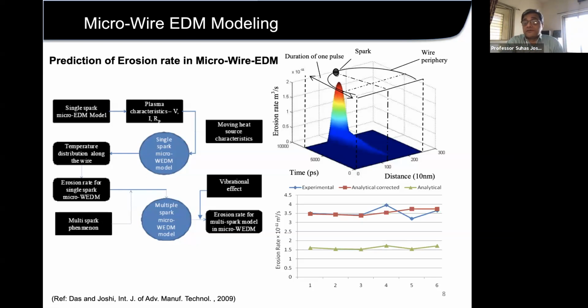Even now, last month, one of my students finished a PhD in EDM, where he developed a model of multi-sparks happening on the surfaces at random time durations and at locations where the interelectrode gaps are smaller. If you have surfaces having asperities, up and down, when the two surfaces come together, wherever the asperities are closer, that's the first point at which the spark begins. Then the next closest asperities spark. But the sparks are not of equal energy at all places, so again that problem comes. We did a small analysis with some assumptions at that time, but we now have a fairly good idea about the distribution of the sparks and the distribution of the energy.